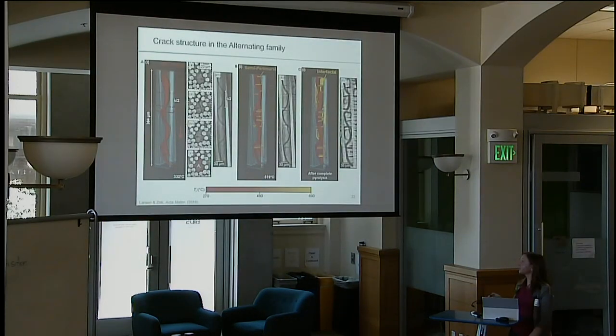So again, 3D renderings with increasing temperature are shown here, along with their corresponding 2D slices, where you can see this crack as it formed and then grew wider and formed new cracks nearby in the same region. So I'd also like to point out that these types of cracks, compared to the perimeral cracks we saw before, are expected to be very favorable because they're inherently connected along their length. So if we want to flow fluid through this region in the later processing steps, this type of crack would be more likely to flow fluid all the way through the composite.